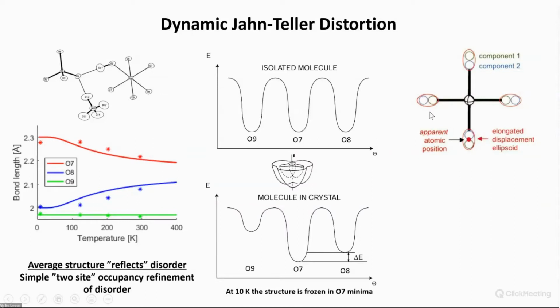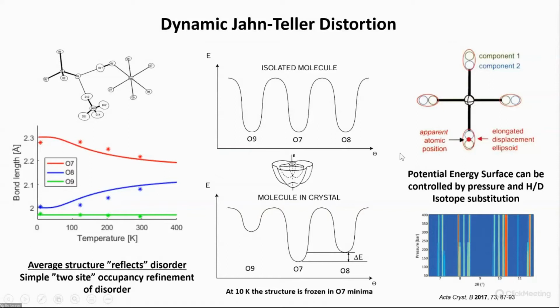And this is all very nice. But the point I want to bring home is that the average structure I get here in Bragg diffraction does reflect the actual disorder, by having these very, very elongated ellipsoids if we model them just in the center. So it's a wonderful structure, and I can talk about it. My students always laugh about it because it's my first study, so I always loved copper Tutton salt.